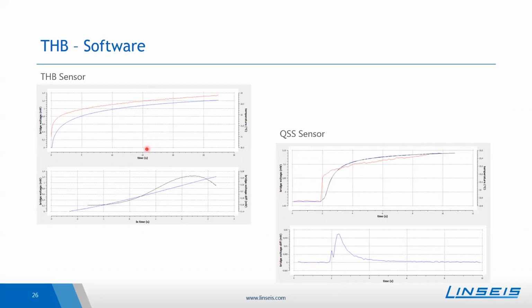Here on top, it depends linearly on the time, and on the bottom, the time is plotted logarithmically, and we see here in blue again the bridge voltage, and the most important curve for the THB is shown here on the bottom in black. It is the derivative of the bridge voltage. During a measurement, one should record a curve which looks like that, so that one can see an increase, a maximum, and a decrease of the derivative of the bridge voltage. From the maximum here, we calculate the thermal conductivity. From the decrease here, we can determine the thermal diffusivity. So one can also have a look at the measurement and decide if the measurement was good or not, also within the software, just with one look.